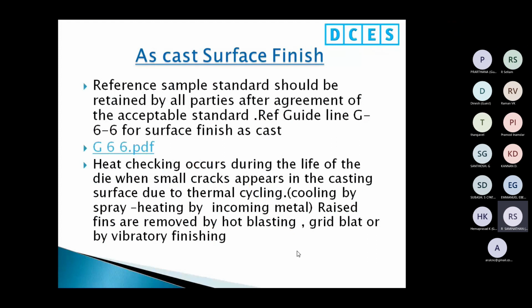And heat checking occurs during the life of the die when small cracks appear in the casting surface due to thermal cycling, cooling by spray, and heating by incoming metal. Raised fins are removed by shot blasting or grit blast or by vibratory finish on the casting itself. For example, if the dies are used after 50 to 60,000 shots, the heat check mark will develop. It will reflect in the casting. It can be removed by shot blasting, grit blasting or vibratory finishing.